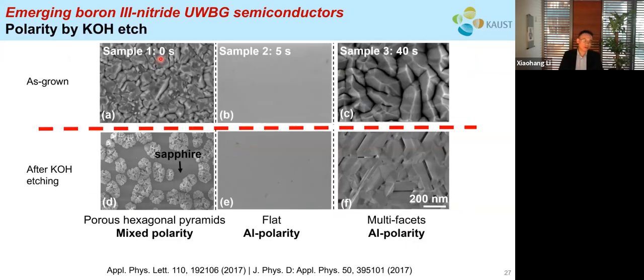After the growth, we used SEM to examine the surface. As I mentioned earlier, nitrogen polar aluminum nitride will have a very rough surface. This is what we saw for the first sample without any preflow. However, for the second sample, the surface is very smooth, indicating that this is aluminum polar. For the third sample, the surface is also very rough, but this roughness is very different from the first sample, because it shows mountain-like or multifaceted features, right? So to further verify the polarity, we used KOH solution to etch the sample. And KOH is very good at etching the nitrogen polar.